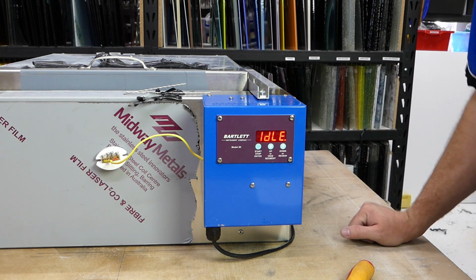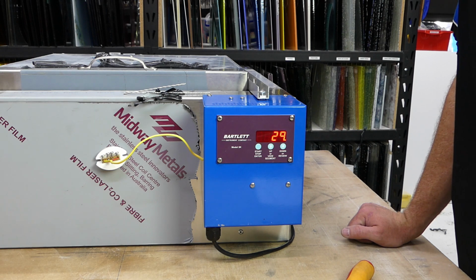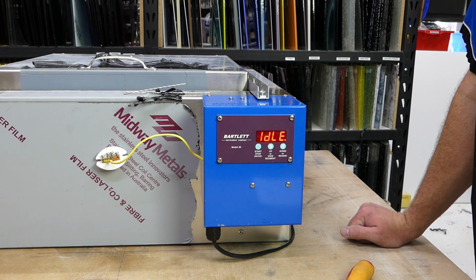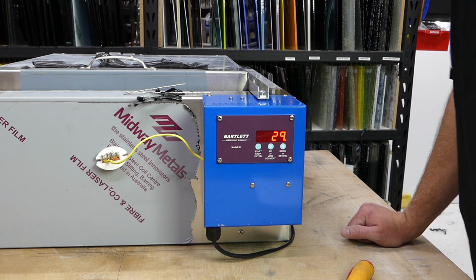You will have noticed that our top temperature for System 96 glass is 770 degrees, whereas the System 96 published temperature is 796 degrees. This is just another effect of the large amount of insulation within the kiln and its heating and cooling time variances. So 770 will give you a full fuse in this kiln, 740 will give you a contour fuse, and 700 will give you a tack fuse.